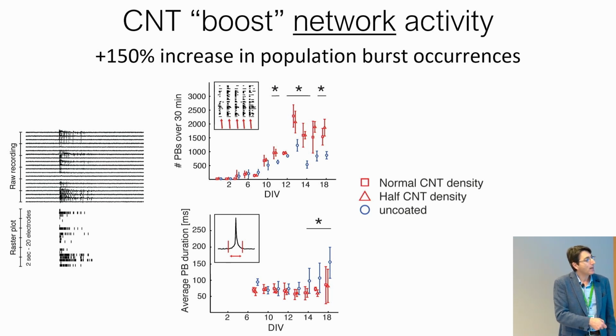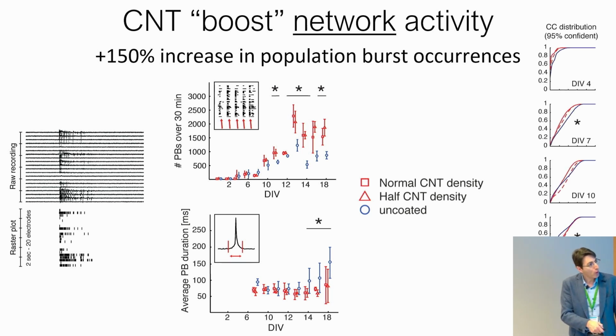So in red, you actually see those MEAs coated with nanotubes showed a systematic higher synchronization. And this has to do with some modification here quantified in terms of the spike trigger cross-correlogram, which is a measure of correlation between spiking activity across different neurons, different electrodes. And here you see the cross-correlation distribution, the cumulative distribution. As the time goes by, you have the red, meaning the spiking activity detected by electrodes that are coated with nanotubes moves to the right. So it seems that they are getting a little bit more connected. We believe that this is not happening pathologically.